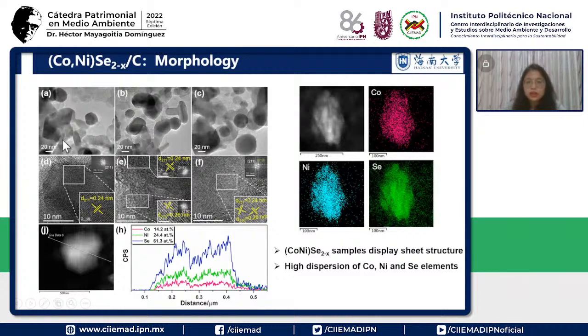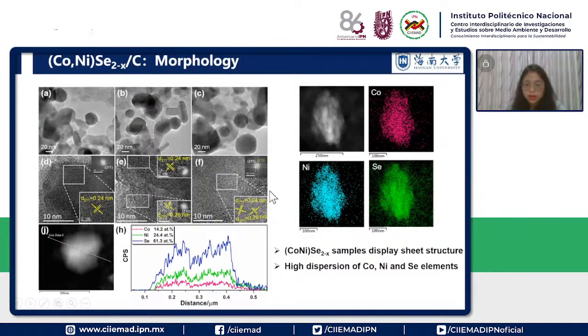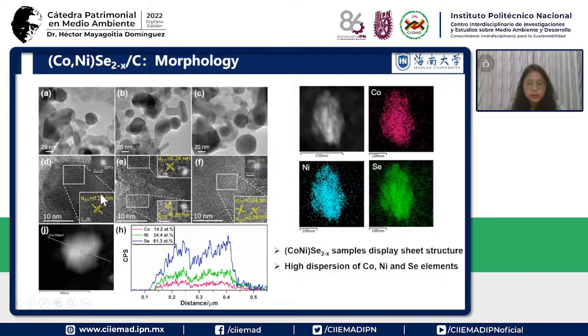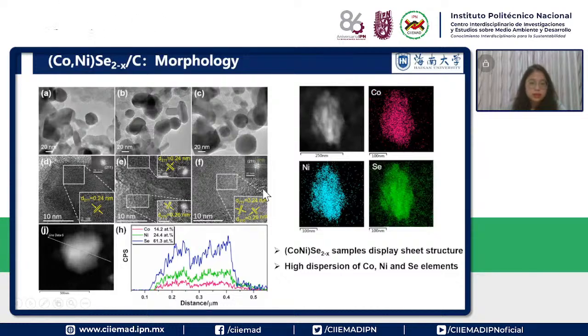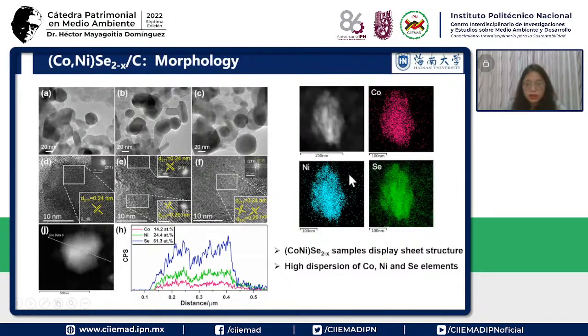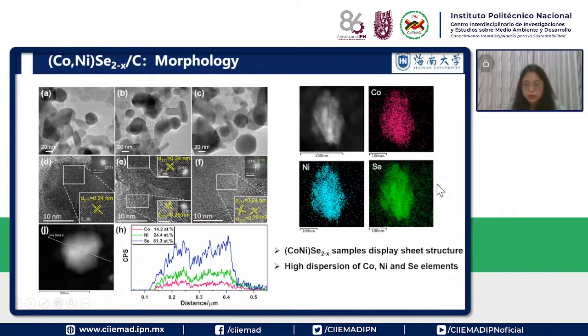And then we find this material has a sheet structure. It's not a particle. The HRTEM further confirms we got the cobalt selenide and the nickel selenide. The cobalt, nickel, and selenide elements show high dispersion.